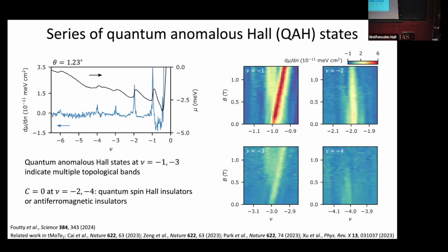And the way to tell that is to apply a magnetic field and see how these states disperse. So from the Streda formula, we know that if you have a state with a non-zero Chern number, then necessarily that will have a diagonal slope in a magnetic field. And indeed, if we look at the state at nu equals -1, there is an incompressible state which is sloped all the way down to zero magnetic field. So this is a quantum anomalous Hall state. We haven't done transport on the system, but at least Streda should be believable. So you should trust that this is a quantum anomalous Hall state.